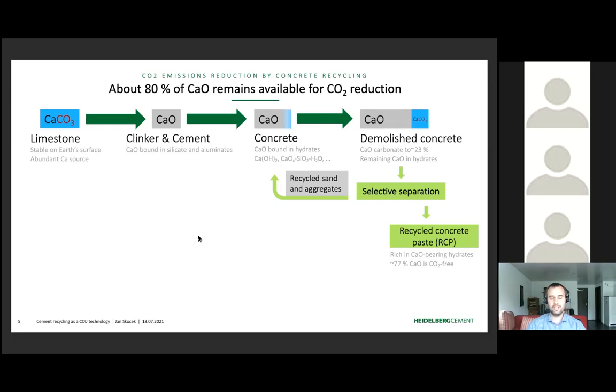To do that, we need to do several technological steps. First of them is what we call selective separation, which is a kind of advanced concrete recycling, whose aim is to split the old demolished concrete into original constituents, into recycled aggregates and sand. What is left is the fine fraction, which we call recycled concrete paste, RCP, where the hydrates are concentrated and also the calcium oxide.